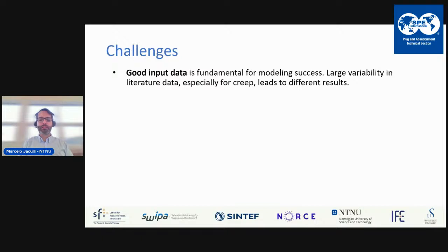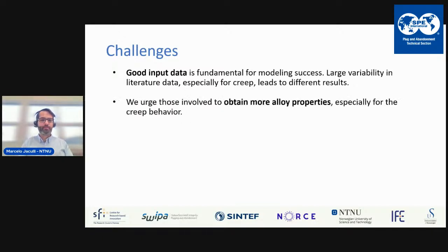As remaining challenges for our research, we came up with a very fundamental claim: good input data is necessary for modeling success. But the problem in this particular application is that you have large variability of input data in the literature, especially for creep. There are several studies looking at the same alloy providing completely different models and parameters, so this needs better testing.